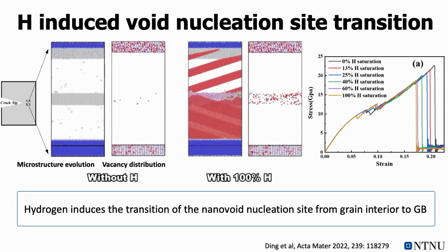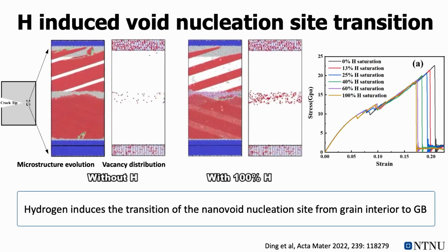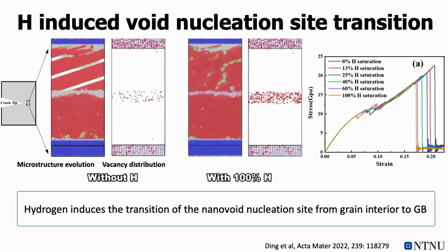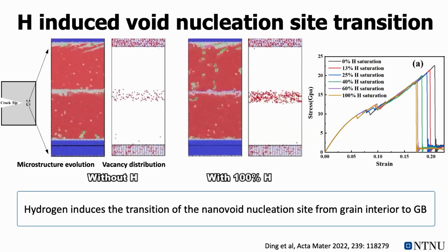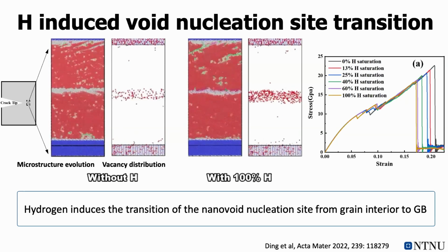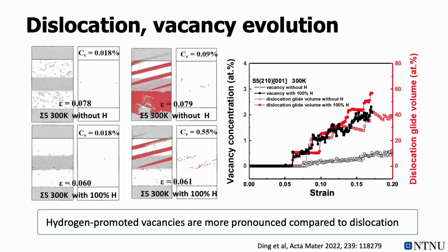And if we look at this tensile curve, it's very clear that when hydrogen enters the material, it induces early plasticity. So it demonstrates the HELP mechanism. And if we look further at this hydrogen-induced fracture mode transition, a lot of us talk about hydrogen-dislocation interaction or vacancy interaction. So, borrowing the advantage of molecular dynamics simulation, we can decompose the hydrogen contribution to the dislocation behavior and to the vacancy behavior.